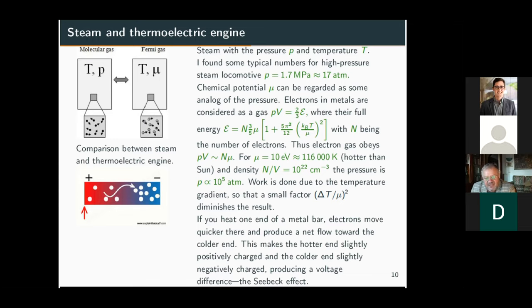In the metal, you do not have molecular gas. You have Fermi gas, a degenerate gas, which has temperature and is characterized by Fermi energy or chemical potential. The chemical potential, the Fermi energy, for different metals is different, but you can easily see that it is expressed as a power of p Fermi. p Fermi determines this pressure. So the role of pressure is played by the chemical potential. So having two different metals and putting them at different temperatures, you create a Carnot engine in some sense.